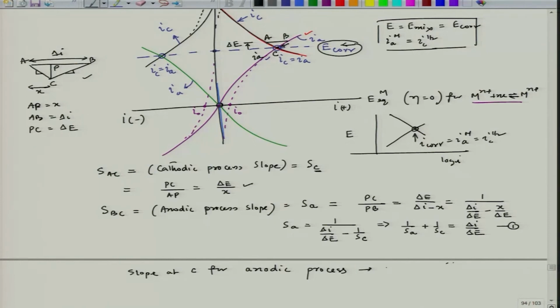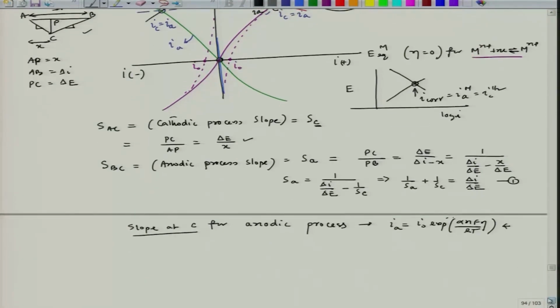so that means I have to find a slope for this. I equal to I0 exponential alpha NF eta by RT, with the factor 2.303. So this equation I have to use just to find the slope at C for the anodic process. In that case I can write this equation as eta, which is nothing but E corr minus E equilibrium, equal to